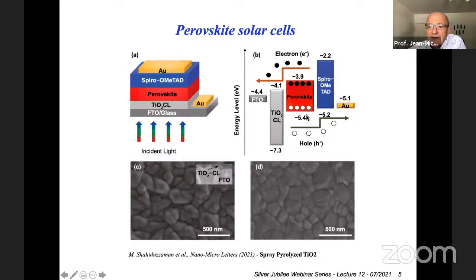The perovskite is a material, I must say, which is an interesting material for solar cells because the exciton lifetime is very short. Actually, the exciton self-dissociates into an electron-hole pair owing to the very large dielectric constant of the material. The perovskite is a lead perovskite, so the binding energy of the exciton in these materials is small. So the electron-hole pair can dissociate spontaneously in these materials at room temperature, which means that we are dealing with